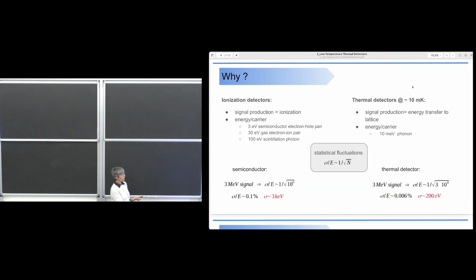While if I use a thermal detector, with the same kind of evaluation, and assuming that my carrier has an energy of 10 millielectron volt, that is quite pessimistic, and I will tell you why, the energy resolution is 200 electron volt, so 1 order of magnitude lower.